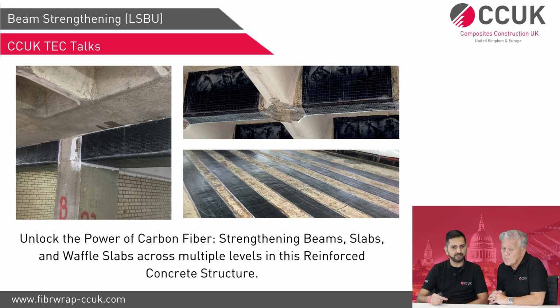So we applied the plate at the underside. We also did the shear strengthening by putting a U-wrap, as we could see in individual waffles. And then we also applied FRP on top of these ribs to strengthen them for hogging moments. So all three types of strengthening were done there, as we do in the beams. And also the primary beams were strengthened for flexure and shear as well.